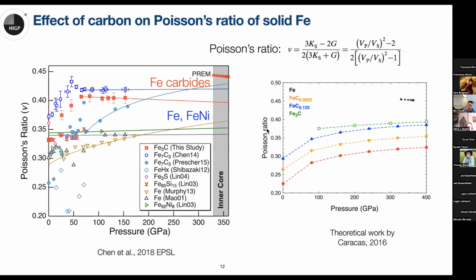Another very important parameter for the Earth's inner core is the Poisson's ratio, which is defined as a function of Vp over Vs. The Earth's inner core has a Poisson's ratio close to 0.45, but most others, including iron, iron-nickel alloys and other iron light element alloys, have a Poisson's ratio that is much lower, below 0.35. And our iron carbide phase, after the spin transition, has a Poisson's ratio that is closer to the seismically observed values. This also agrees well with one of the theoretical works about the Poisson's ratio of iron and iron-carbon alloys at high pressure. So by increasing the amount of carbon in iron alloys, you could elevate the Poisson's ratio.